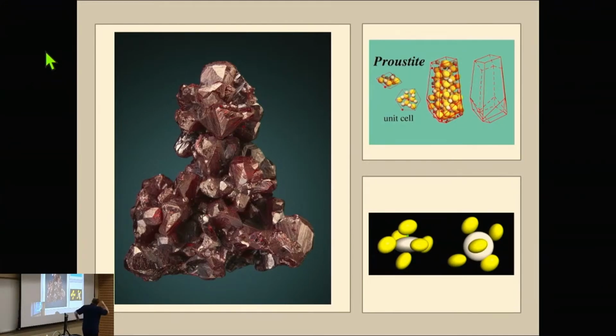If I turn it on its side and look straight down it, I typically think about the silver interacting with two sulfurs, because the sulfurs will form a pyramid with, at the apex of that pyramid, either the arsenic. But in fact, I can interact with 6. 4 around and 1 above and 1 below. And so at any given time, I'm going to be interacting in that particular direction. So there's a bond that's between those, but that bond changes with time. And that bond is very highly sensitive to temperature.